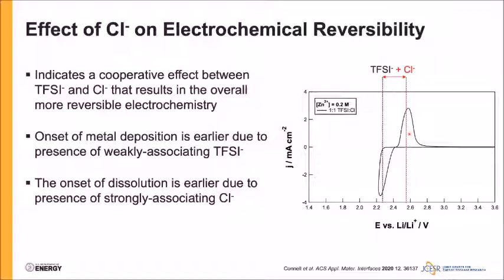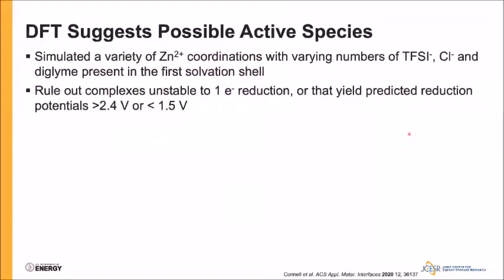Now that said, this is at this point a little bit of speculation based just on voltammetry. To determine whether this effect is reasonable, we turn to density functional theory to investigate some potential active species that might be leading to this behavior. What we did is simulate a variety of different zinc coordinations with varying numbers of TFSI anions, chloride anions, and diglyme solvent molecules in the first solvation shell.